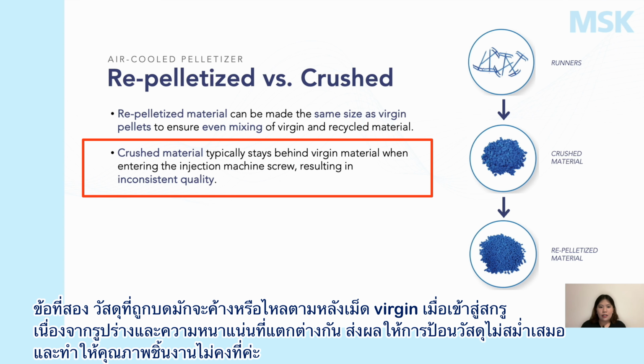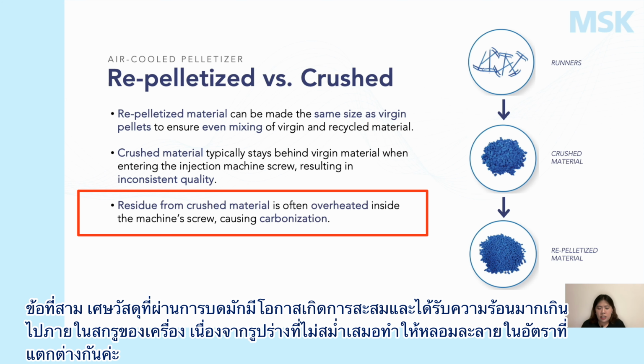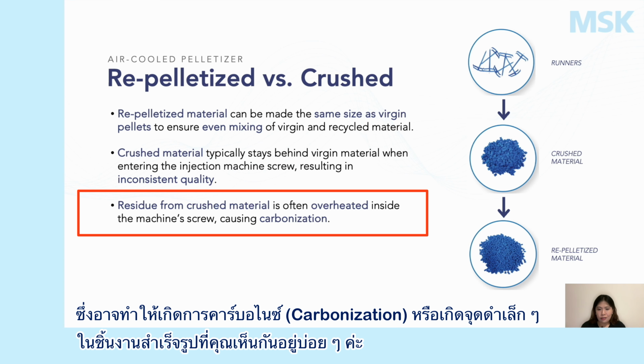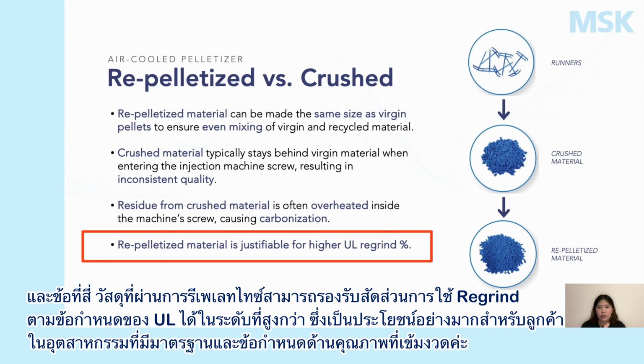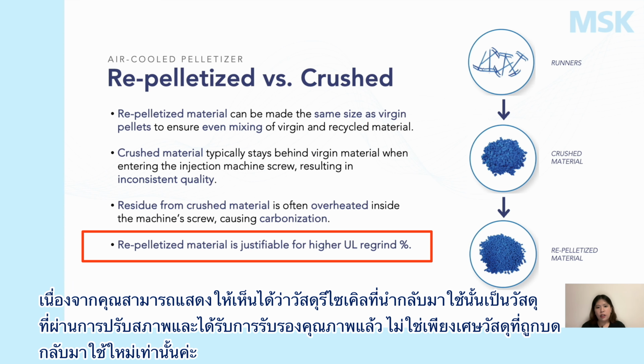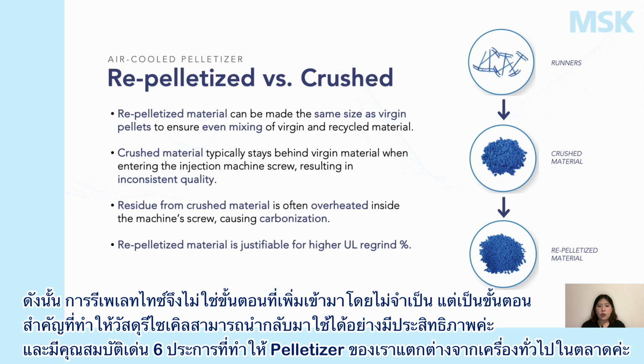So the result is inconsistent feeding and inconsistent part quality. Third, residue from crushed material is often overheated inside the machine screw because the irregular shapes don't melt at the same rate. This can cause carbonization, which is those black specks you see in finished parts. And fourth, repelletized material is justifiable for a higher UL regrind percentage. For customers in regulated industries, this matters a lot because you can demonstrate that your recycled content is qualified material, not just crushed scrap. So repelletizing isn't an extra step, it's the step that makes recycled material useful.